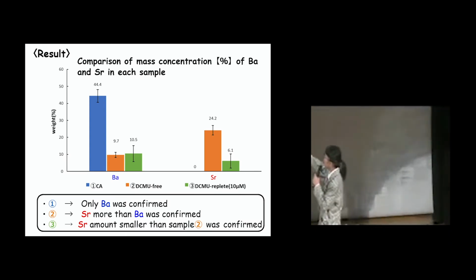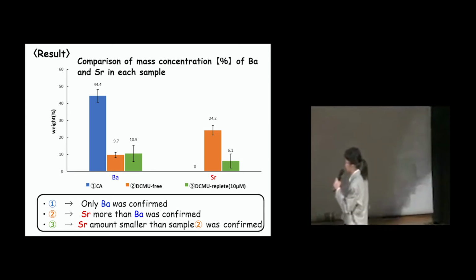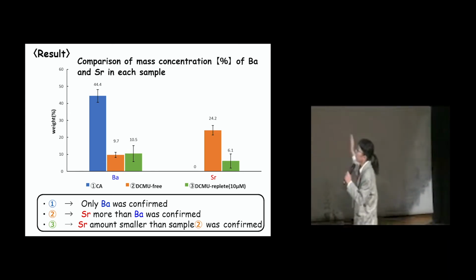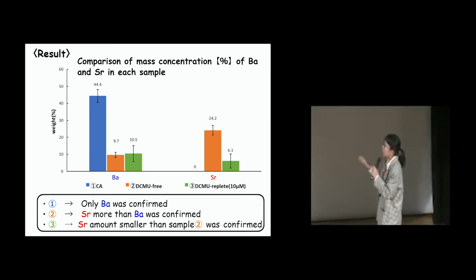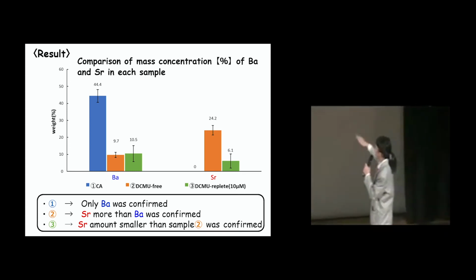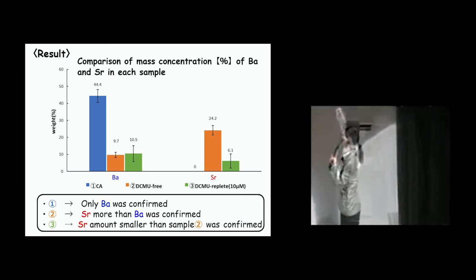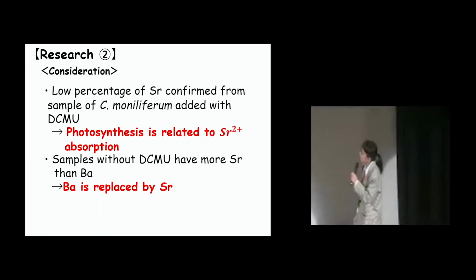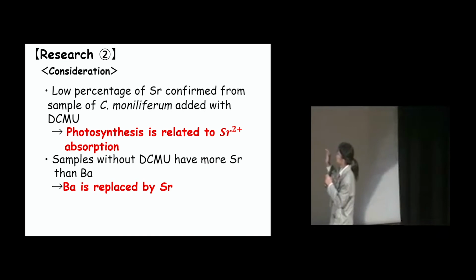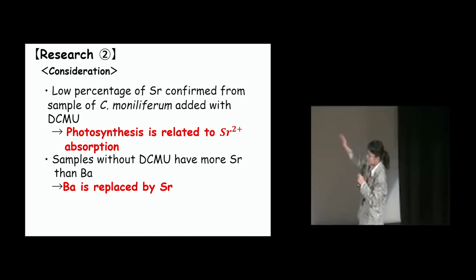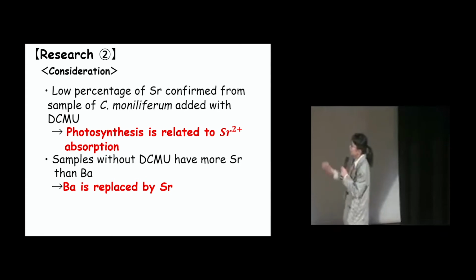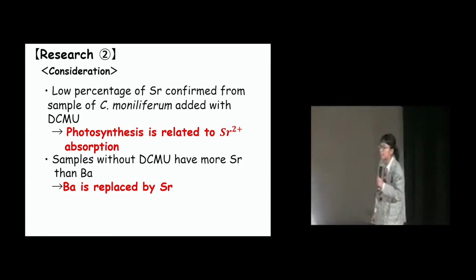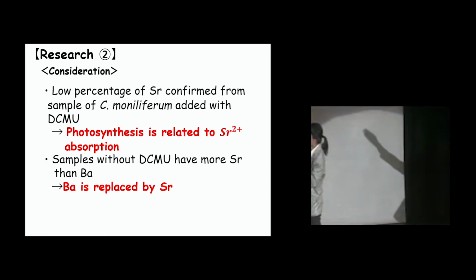Sample 1, only barium was confirmed. And sample 2, strontium more than barium was confirmed. Sample 3, strontium amount smaller than sample 2 was confirmed. Consideration 1, a low percentage of strontium was confirmed from the sample of Closterium moniliferum added with DCMU. Photosynthesis is related to strontium ion absorption. 2, samples without DCMU have more strontium than barium. Calcium is replaced by strontium.